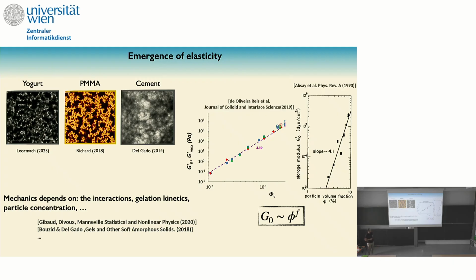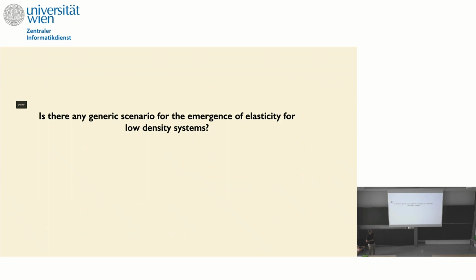The mechanical properties are also very complex in the sense that they depend on the interaction between the particles. They depend, as I told you, on the kinetics of gelation, so whether you quench your system fast or do your experiment slowly, but also on the particle concentration and so on and so forth. So this makes it a very challenging system to understand. In the first part of the talk, I will try to convince you that there is a generic scenario for the emergence of elasticity in this system at low density. And the answer is that the elasticity emerges from a rigidity percolation transition. I will define what a rigidity percolation transition is in the next slide.